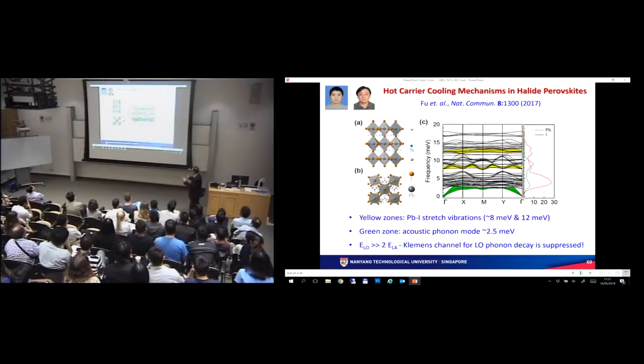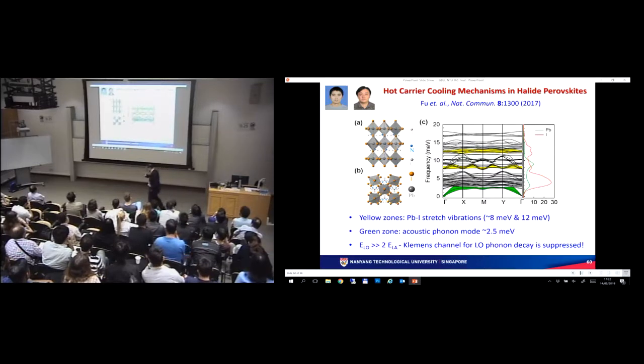Now, from DFT performed by Xu Qiang, the phonon band structure, the yellow zones tell us the LO phonon levels, and the green zone tells us the acoustic phonon modes. There is a clear mismatch between your LO phonons and 2 times the LA phonons. This suggests to us that the Klemens process, where an LO phonon decays into 2 acoustic phonons, is actually suppressed, and that's the main reason why we think that the hot phonon bottleneck is still intact in these halide perovskites.